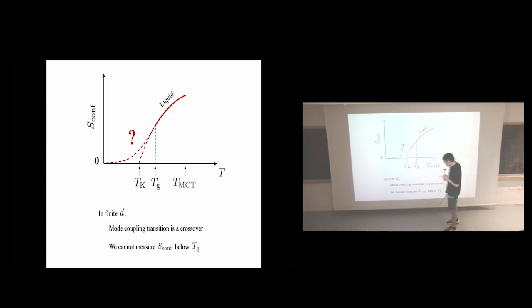Okay? And also, we cannot measure configurational entropy in equilibrium below the experimental glass transition temperature that Camille introduced. Because typically, experimentalists can wait up to 100 seconds. If the relaxation time goes above 100 seconds, the system goes out of equilibrium, so we cannot measure configurational entropy. Therefore, we have to rely on crude extrapolation, maybe in favor of a Kauzmann transition, or a completely avoided transition with a smooth landing toward zero configurational entropy. So this is the current status. Nevertheless, random first order transition theory is very useful to understand the nature of glass transition.